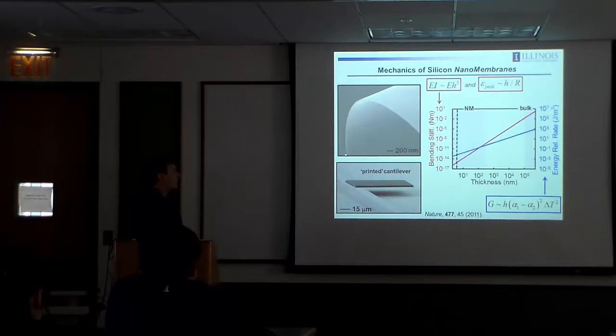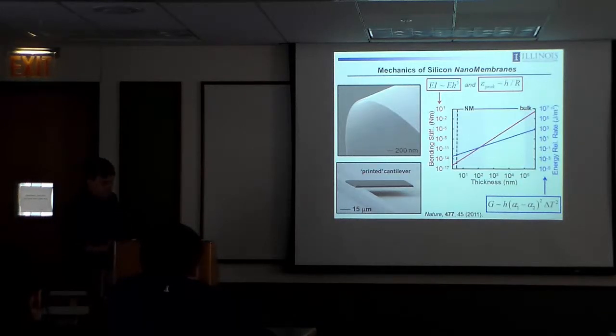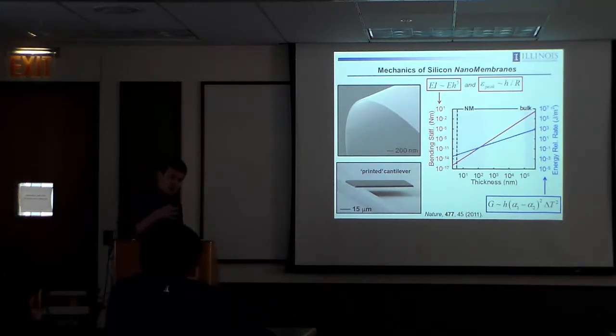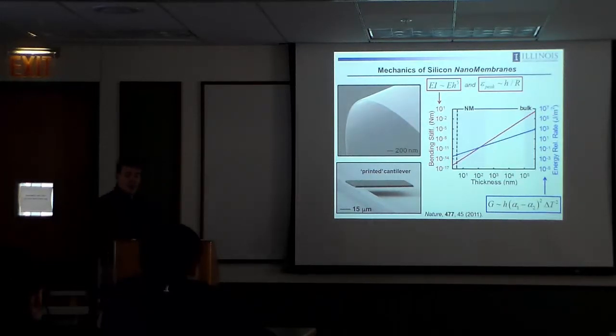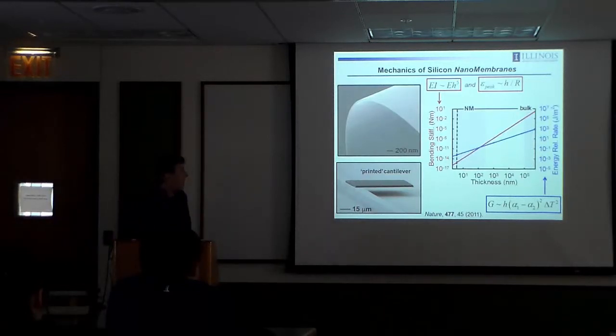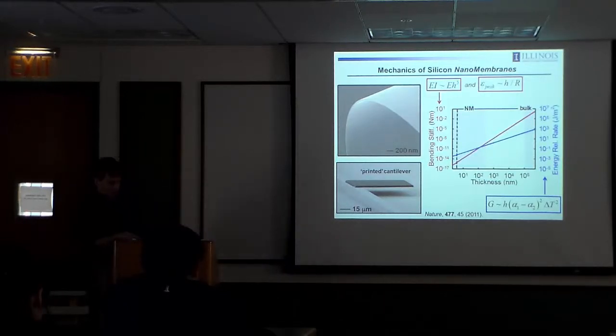Initial instinct may be, okay, well, we'll replace the wafer with this thin sheet of silicon and then you'll build the devices that way. That doesn't work either, though, because this is very thin and floppy and flexible, but it's also very fragile. So you have to think about it not as a device platform, but as a building block material for devices that you might construct on a sheet of plastic or a piece of rubber. And in those cases, you have to grapple with a problem in heterogeneous integration. So how do you put silicon on silicone and manage that interface so that it remains robustly adhered during practical use? And there, that would be daunting. If you were taking a chip of silicon and trying to glue it to a piece of rubber, you'd have a hard time doing that.